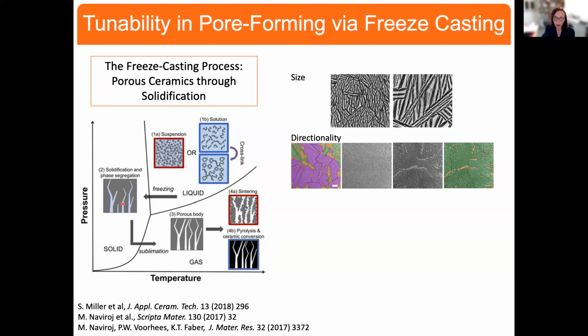And in fact, we can control that by, in addition to this cold plate, putting some sort of a template at the base of the cold plate, where we can then define the places where the solid will nucleate. And we see this here. This is just a series of colorized images that tell us which pores are standing straight up, which are the ones in green, and which are sort of off axis here.